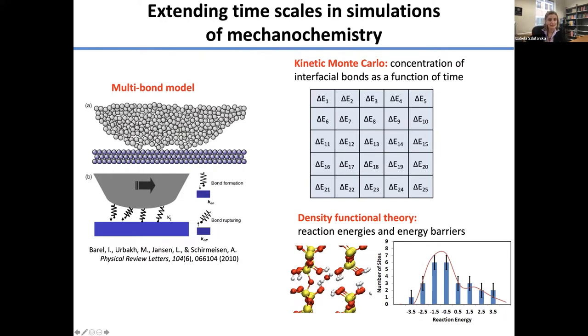And then we assign these energies to our bonding sites on the surface. Now, these energies can be turned into probabilities because basically they can be turned into rates of reactions. And based on this probability, we can statistically evolve the interface to say, as a function of time, how much bonding we're going to see. In other words, how much the static friction is going to increase, since, as I said, static friction is proportional to this number of bonds.